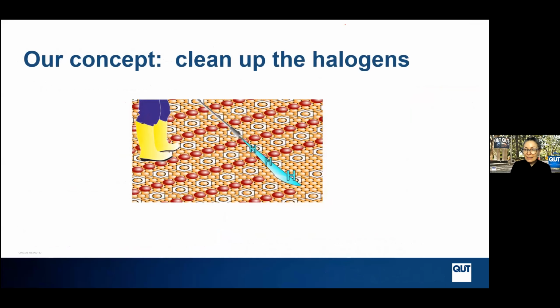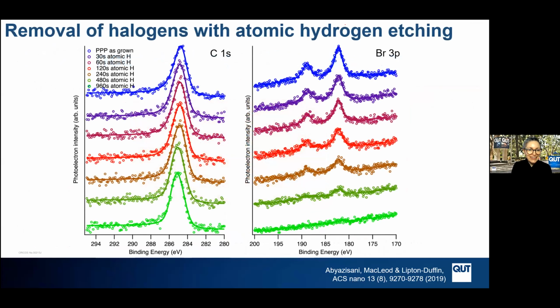And we had an idea of how we could do this based on work from Mikey Storr's group, where she had shown that molecular hydrogen can reduce the prevalence of retained halogens on the surface. We went one step further and we used atomic hydrogen from our hydrogen cracker that we happen to have in our system. So what we did was to just spray it at the surface and to watch the bromine 3p core level disappear. You'll notice in carbon 1s, there's really not a big difference, but we're able to remove all of the bromine from the surface.